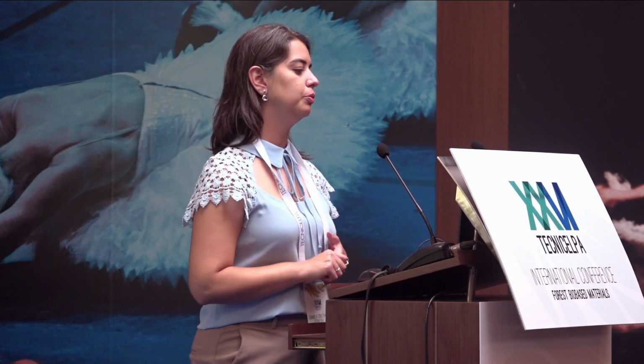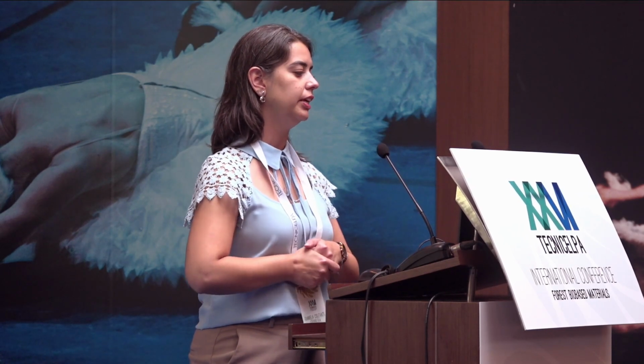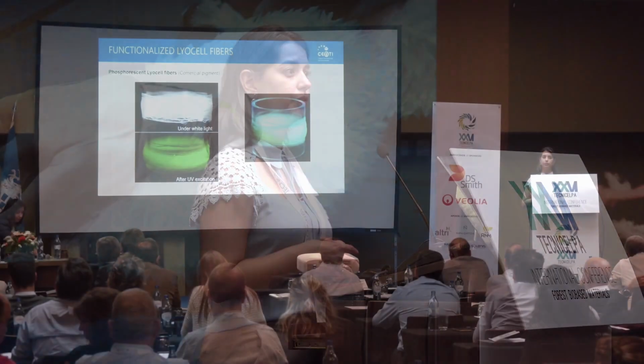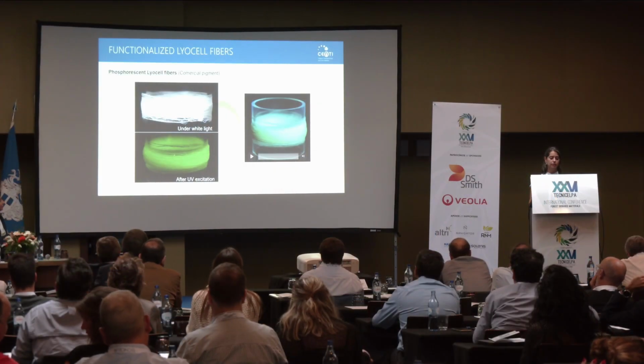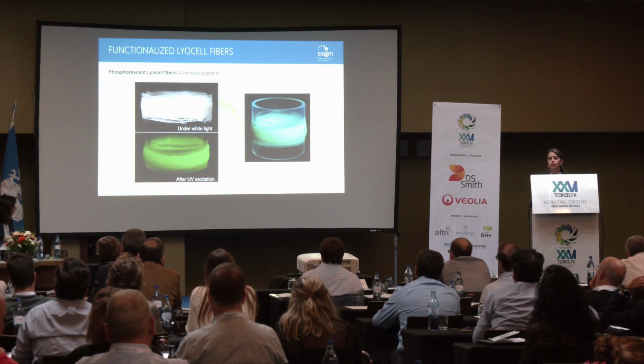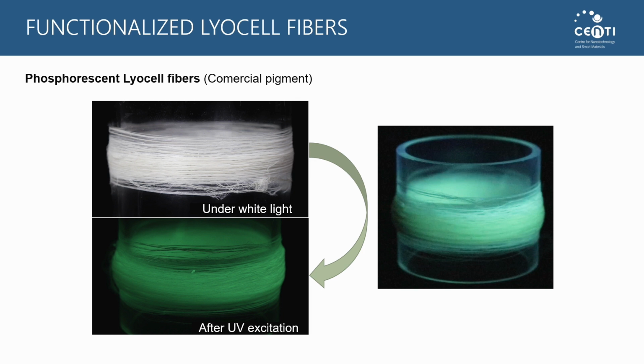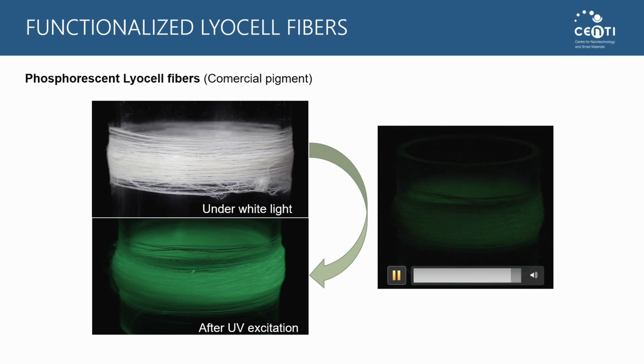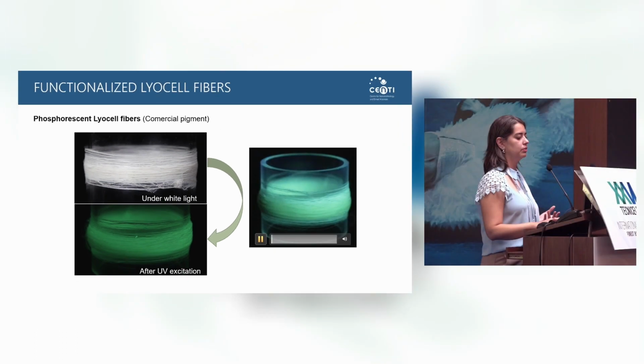And for the fluorescent fibers, with the commercial pigment, here is an example with the phosphorescent pigment, and here is the fiber in white light. At white light, we cannot see that there is something in the fibers, and under UV light, we can see that it's emitting light, and here a video showing the phosphorescent effect. When we switch off the UV, it continues emitting light.